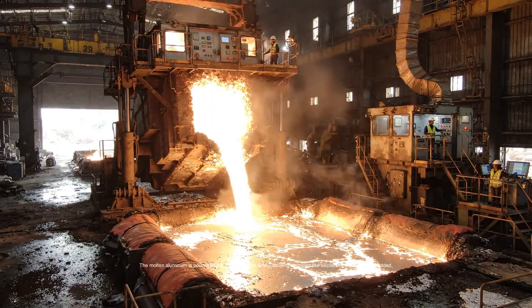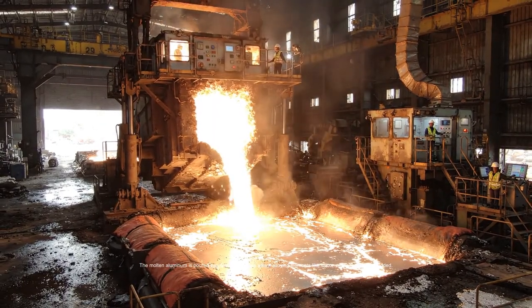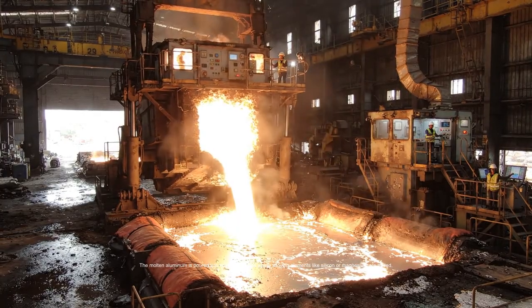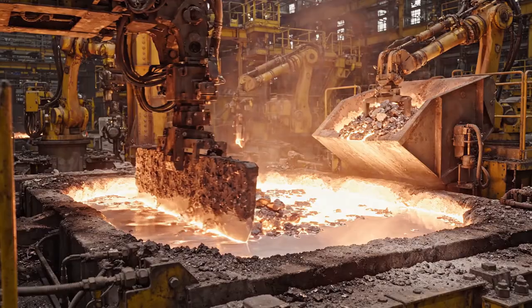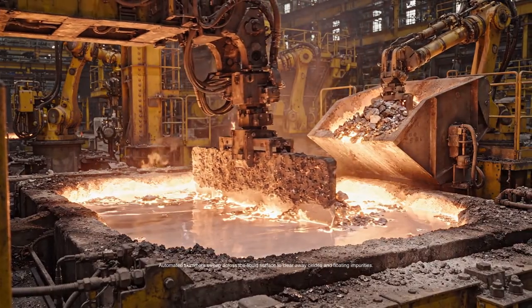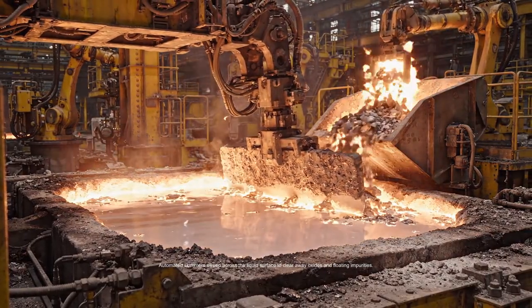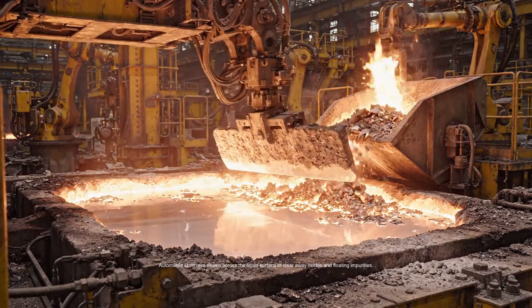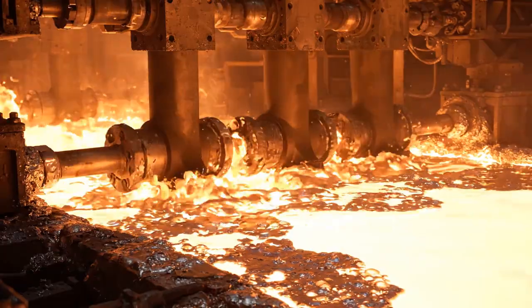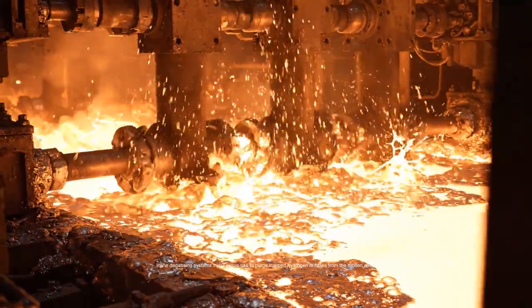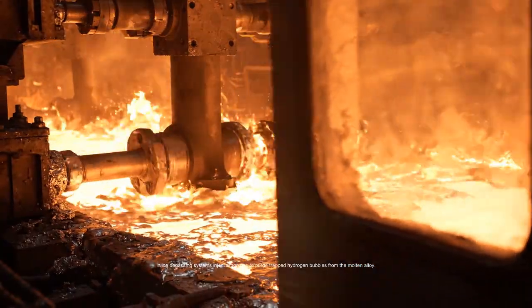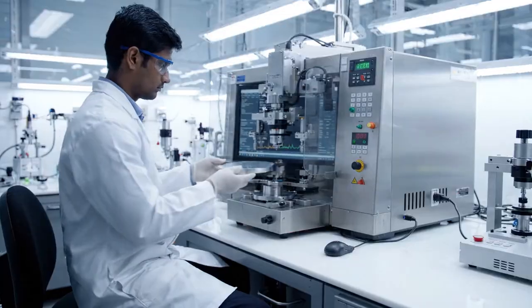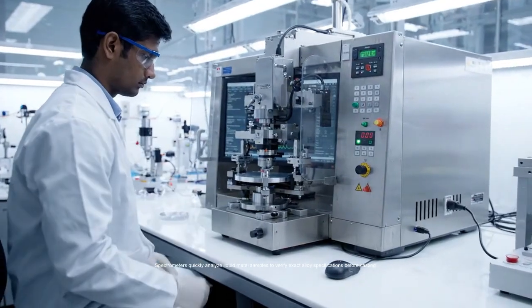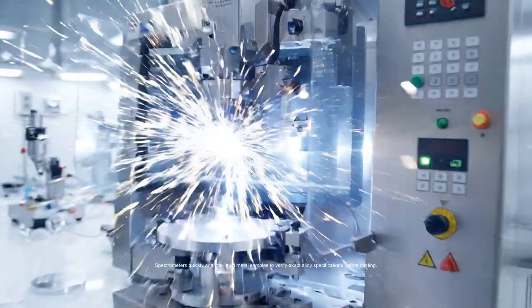The molten aluminum is poured into holding furnaces, where alloying elements like silicon or magnesium are added. Automated skimmers sweep across the liquid surface to clear away oxides and floating impurities. Inline degassing systems inject argon gas to purge trapped hydrogen bubbles from the molten alloy. Spectrometers quickly analyze liquid metal samples to verify exact alloy specifications before casting.